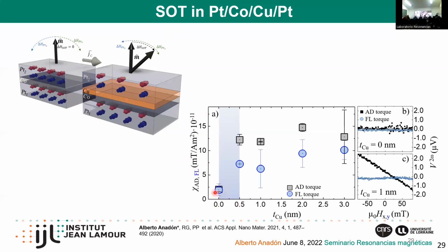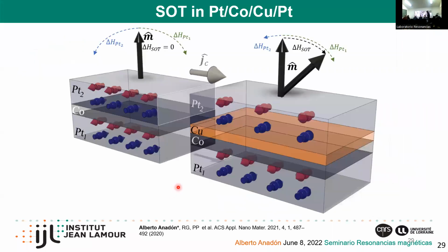And what we observe here is that when we introduce this copper interlayer, the spin orbit torque is increased significantly, both the damping-like and the field-like torque. So for no copper, we see almost no torque. And when we put some copper in it, the torque is much higher. And what we are seeing here is basically we are breaking the symmetry somehow, and we are introducing a spin orbit torque because the effective SOT coming from one layer is different from the other.